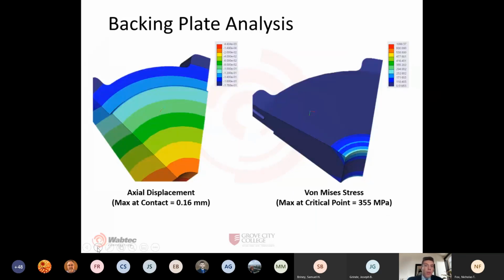So due to the symmetry of the backing plate design, a cyclic symmetric constraint was used in the finite element analysis. This constraint helped simplify the analysis and improved its accuracy as well as speed. The figure to the left shows the axial displacement of the backing plate resulting from the 58,700 pound load. The max displacement at this sleeve contact surface is 0.16 millimeters. This result is less than the maximum allowable deflection of 0.26 millimeters, and this result gives the team confidence that we'll be able to maintain that sleeve seal.